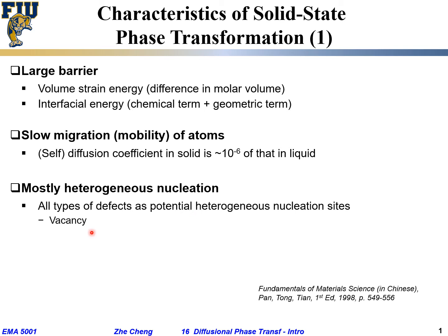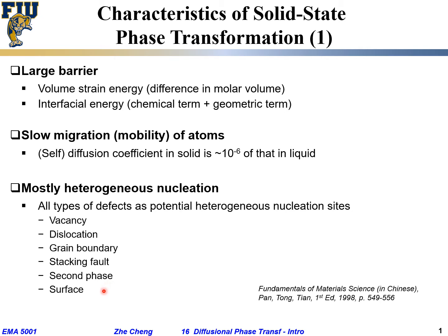For example, vacancies are distributed throughout the crystalline solid. There are also dislocations — linear defects where phase transformation can occur — and grain boundaries, which are quite often the location for many solid-state phase transformations to initiate because atoms are packed more loosely there, accommodating strain energy and interfacial energy. Stacking faults, secondary phases introducing extra interfaces, and the material surface can also be preferred locations for heterogeneous nucleation.